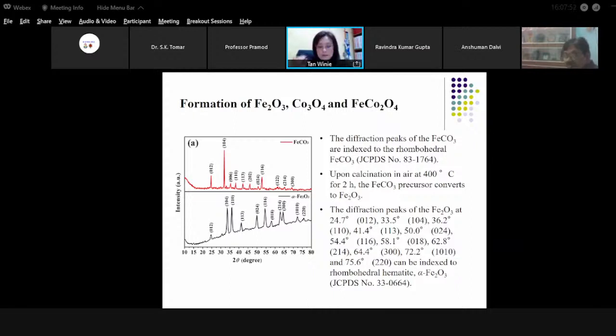The structural properties of the as-prepared samples were characterized by XRD. You can see that the diffraction peaks of the iron carbonate, which is the precursor to the iron oxide, can be indexed to the rhombohedral phase according to the library. Upon calcination, the precursor converts to the iron oxide. We matched the diffraction peaks of the iron oxide with the library, and these peaks can be indexed to rhombohedral hematite, iron oxide.